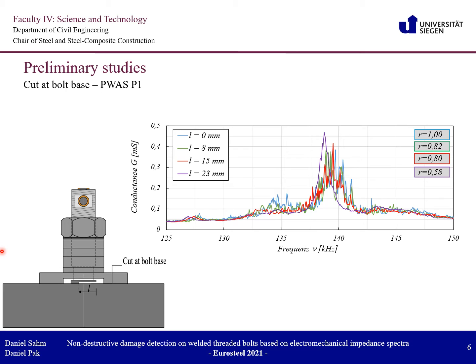In contrast to the behavior of the system under increasing preload, a slight shift of the resonance to a lower frequency range can be observed with increasing cut depth. You can see it right here. Between the damaged 8 mm and 23 mm series of measurements, a change in the structure can be determined with the help of correlation only, as no clear trend is discernible with visual observation of the spectra.